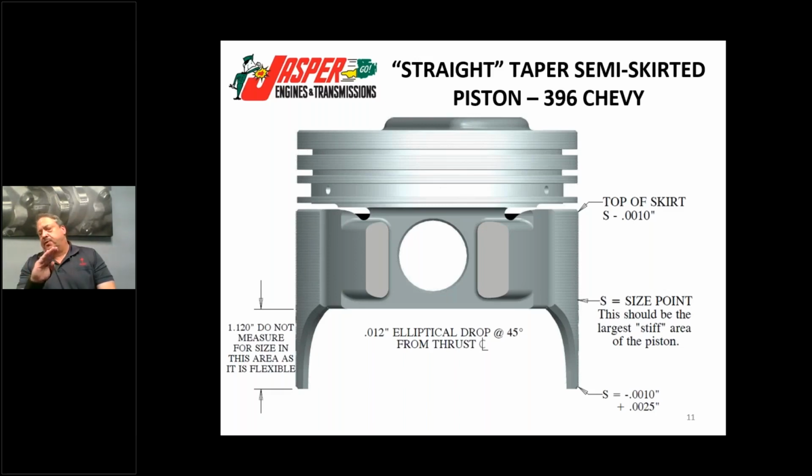So if I'm able to put a 0.5 thousandth skirt coating per side, such as a D10, I just really help my clearance by 1,000ths. And you do not need to measure for that. As I said, most of our abradable coating is actually an interference fit. They slide in nice. They work really well.